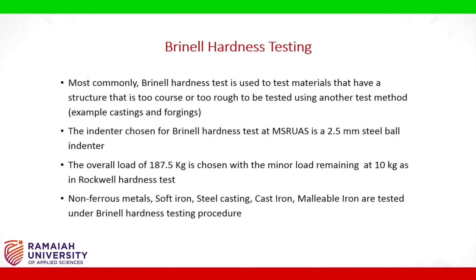Most commonly, Brinell hardness test is used to test materials that have a structure that is too coarse or too rough to be tested using another test method, for example, castings and forgings. The indenter chosen for Brinell hardness test at MSRUAS is a 2.5 mm steel ball indenter. The overall load of 187.5 kg is chosen with the minor load remaining at 10 kg as in Rockwell hardness test. Non-ferrous metals, soft iron, steel casting, cast iron, malleable iron are tested under Brinell hardness testing procedure.